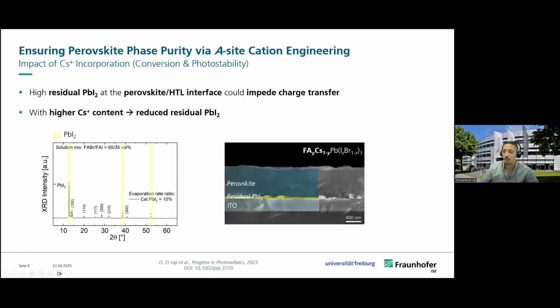As you can see here in the XRD, we have a high intensity of the lead iodide peak that can also be seen in SEM at the interface. And of course, this insulating material can lead to issues in charge extraction, in particular hole extraction if we have a PIN perovskite subcell. Now, we thought that the issue might come from the fact that we do not have enough A-site cations at the buried interface that could participate in, let's say, the formation of a perovskite crystal structure.